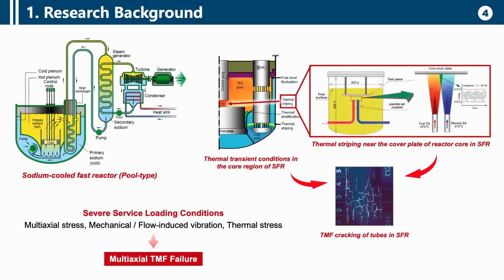This example is for the sodium cooled fast reactor, which we call the SFR. Their thermal transient conditions in the SFR, and also thermal striping near the cover plate of the reactor core, induce thermomechanical cracking of tubes in the SFR. There are several service loading conditions, such as multi-axial stress, mechanical flow-induced vibration, and thermal stress. So in this study, we concentrated on multi-axial thermomechanical fatigue failure.